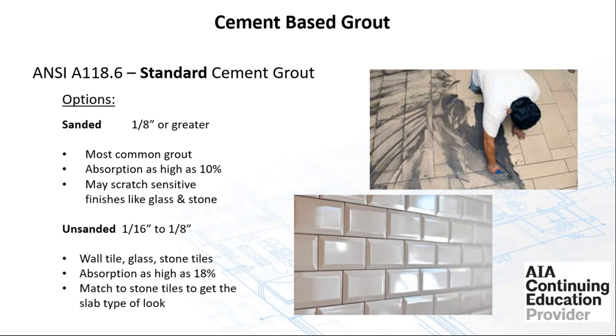So any question, do a mock-up just to make sure which grout will be the best and that we're not going to have any scratching on the tile itself. The unsanded grout goes from a 1/16 up to an 1/8. Primarily used for wall tile, glass, or stone tiles. High absorption up to 18%. A lot of times it's matched to stone tiles to get the slab type look. In other words, not focusing on the tile.